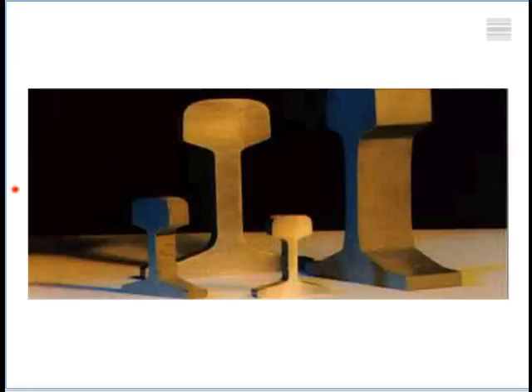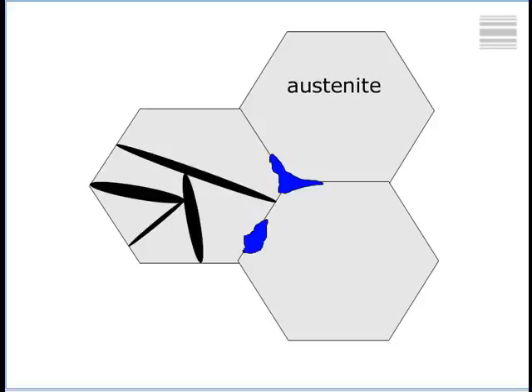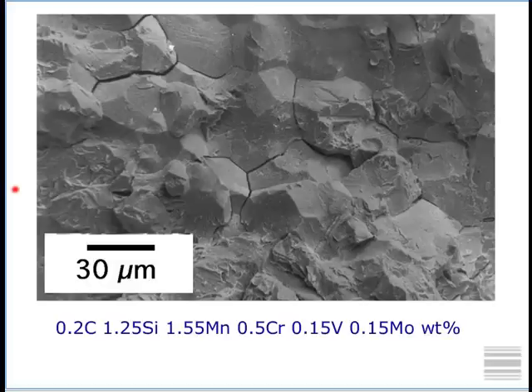And the reason is that displacive transformations are confined within the austenite grains in which they nucleate. Diffusional transformations can cross the boundaries of austenite and destroy them, which means that you cannot segregate impurities to the austenite grain boundaries. Here, even after you form bainite and martensite, you still have the prior austenite grain boundaries where impurities, such as phosphorus in particular, can segregate. And they cause fracture. As you can see here, these are austenite grains exposed by phosphorus segregation.